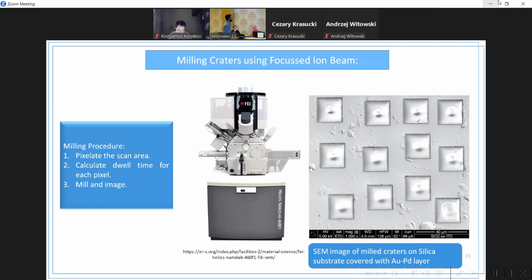We do that by using a focused ion beam. This is an image of the craters that we started milling. You can see this dimple in the center of all these images - the little dimple that we were able to create. All of these dimples have a different radius of curvature while keeping the same depth.